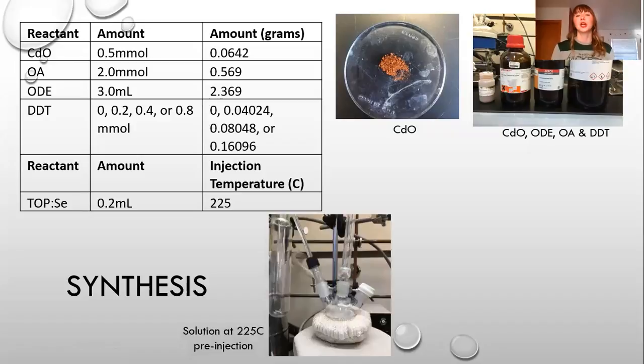So we add those to our round bottom flask first. And as you can see in this picture, our flask is covered with a stopper on one side. In the middle here, this tube is linking it to the Schlenk line, so I can control the atmosphere in this flask. And then finally, we equip it with a temperature probe because this gets up to over 220 degrees Celsius. And when it hits that temperature, obviously the initial solution is going to be kind of this murky red because of the cadmium oxide.